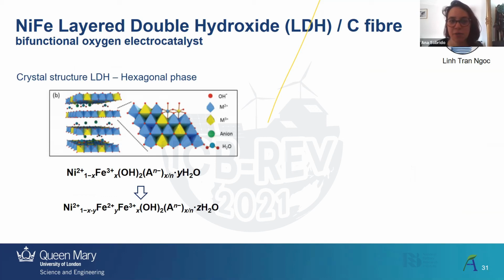I have Lynn, a PhD student in the group, who is working on this type of materials: nickel iron layered double hydroxides supported on carbon fibers, and these carbon fibers are also lignin-derived. These layered double hydroxides present a hexagonal phase. I don't know if you've seen these sort of materials before, but they have different octahedra. Some of them have a cation in the 3+ oxidation state, and some 2+. Then they have these layers where they can have water molecules. They can also have other anions depending on synthesis, mostly carbonate.